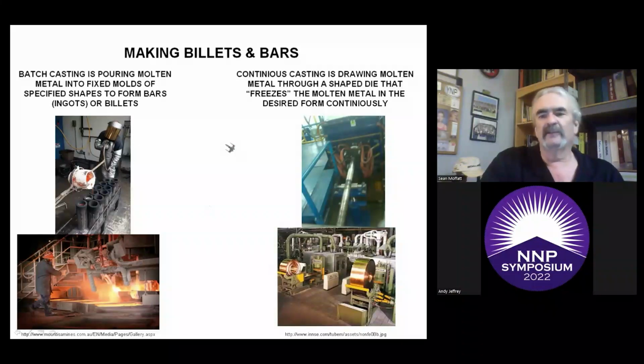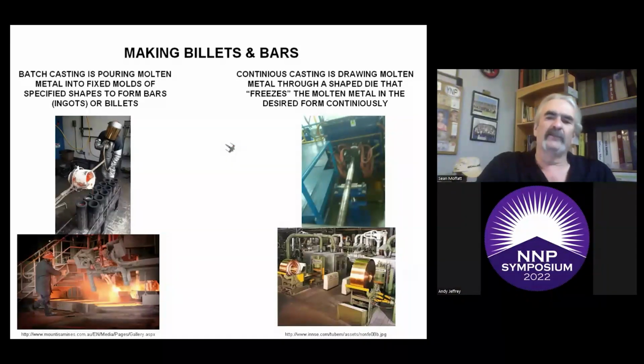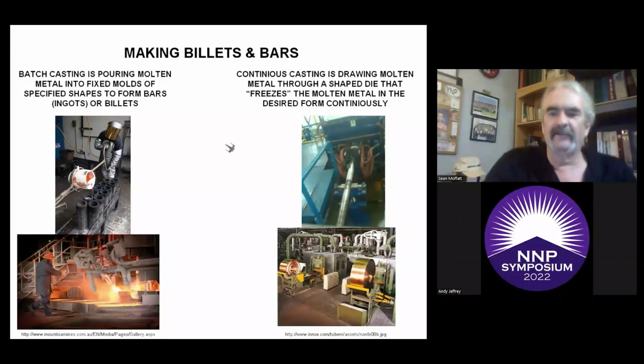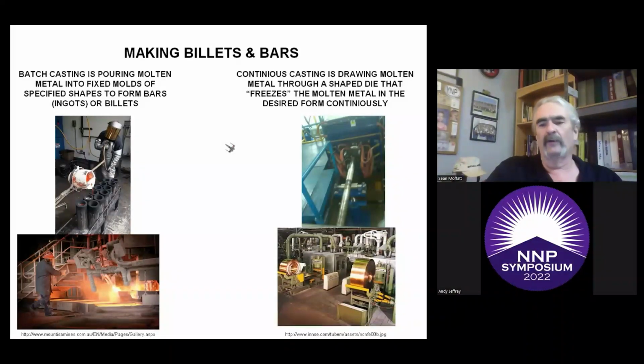All right, now continuous casting is a process of drawing molten metal through a shaped die that freezes the molten metal into a specific form continuously. Here you can see this is a silver bar or silver billet starting to come out of the continuous caster as a steel starter bar starts pulling it out. And if you didn't chop this off every so often, if you just kept feeding it silver, it'd basically wrap around the world and just keep going and going and going. All right, so it can come out in bars, it can come out in squares, or down here you can see they come out in strips, which are then coiled up for further processing.